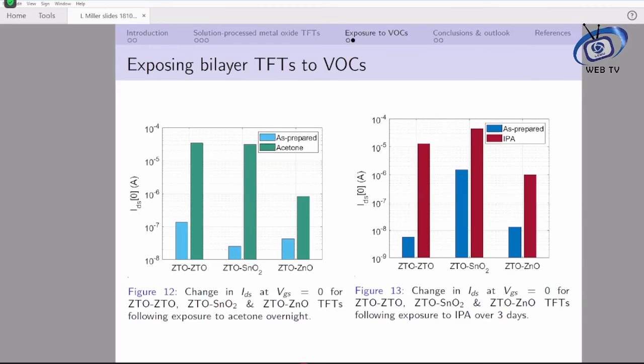The change in drain current at 0 applied gate bias was computed and confirmed that the sensing mechanism was analogous, as the conductivity of the channel increased in every case following exposure.